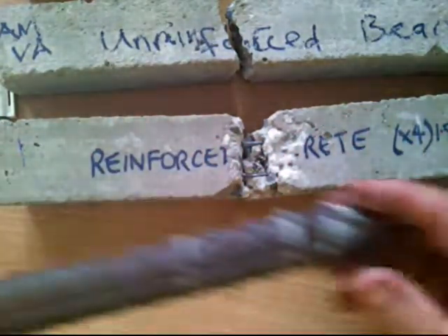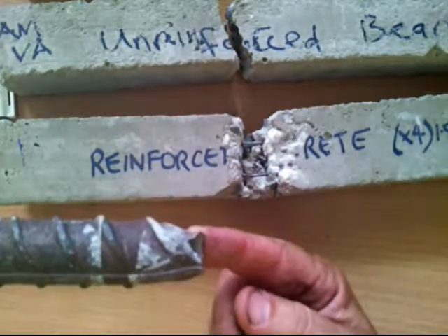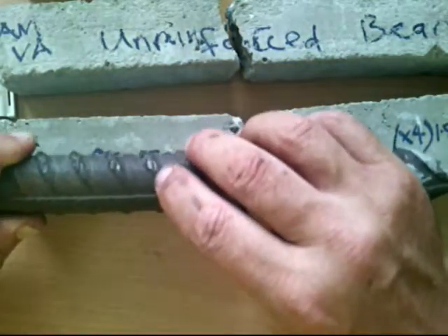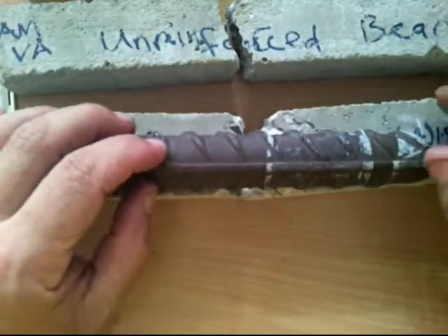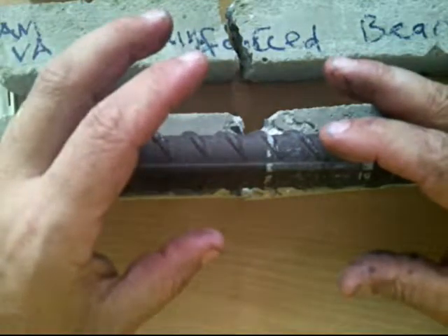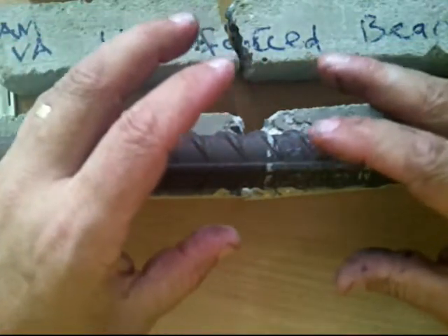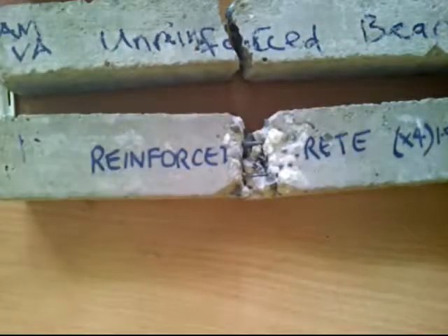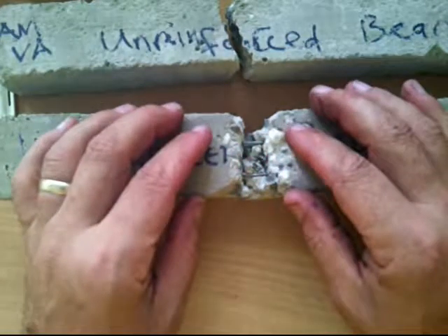So if you can imagine elastic bands, they do stretch, and they're stretched like this one over here, but not to failure like this. And when they're stretched, in their stretched state, the concrete is cast. When the concrete sets, it grips over here, then the tensile pressure on the beam is released, is taken off, and the beam then contracts, trying to go back to its original dimensions. Strain energy is abundant in there, and when it contracts, it places the concrete under compressive strength, and that compressive strength has to be overcome before failure can occur.